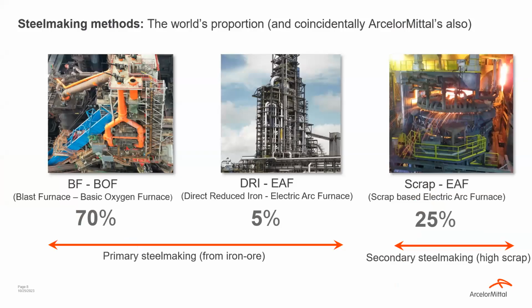Here on this slide, I think it's important, first of all, to get a rough idea of the global distribution of steel manufacturing worldwide. These numbers are coming from the World Steel Association, but within ArcelorMittal, we somehow follow the same trend, in the sense that we have a big majority of the steel produced from the blast furnace, basic oxygen furnace routes. A very small percentage at the moment through DRI, direct reduced iron. These two production routes are labeled as primary steelmaking routes because we're using iron ore. Then we have roughly a quarter which comes from EAF, electric arc furnace routes, which use scrap, which is based on recycling, and which is usually labeled as secondary steelmaking.